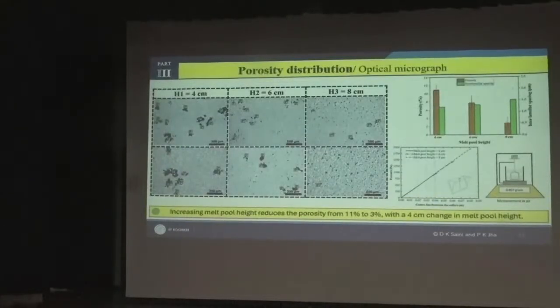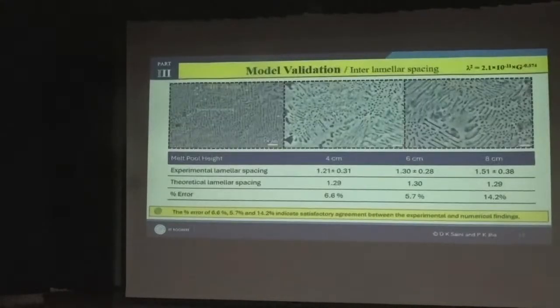We will move forward. A few things which we saw, that there is a lot of porosity change, and you see how we changed the melt pool height from 4 to 8, and see the difference in the porosity levels. So that is changed because of hydrostatic pressure from the top, maybe that was the reason.